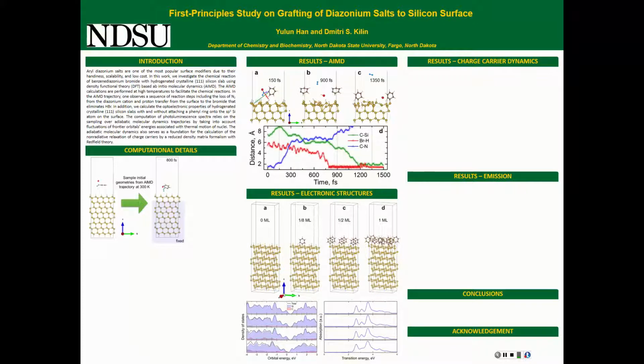Well, questions should be addressed to the author. Okay, so when I did experiments, the silicon surface exposed to the environment is covered by silicon oxide. When it is put into ultra high vacuum, and we degas it and apply heat, then there is no silicon oxide layer anymore.